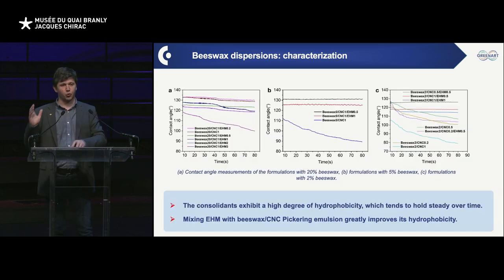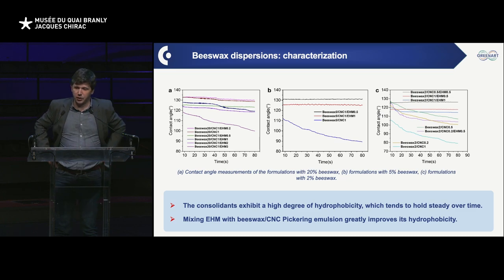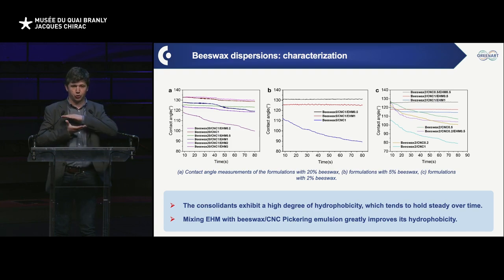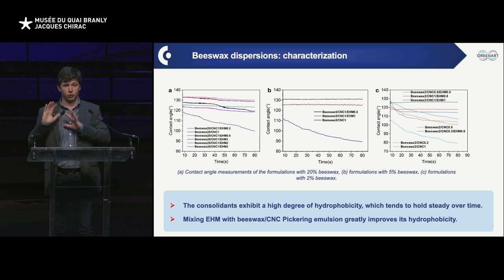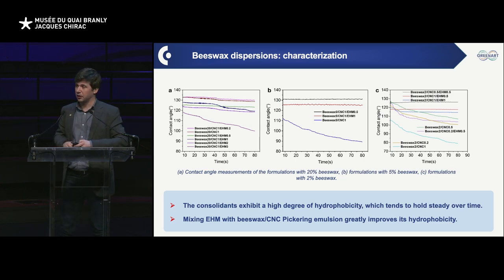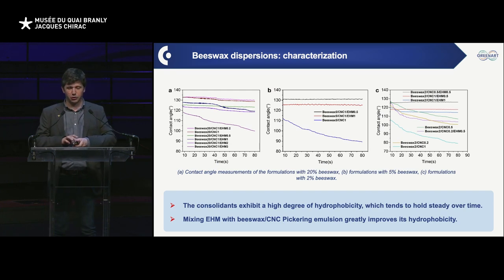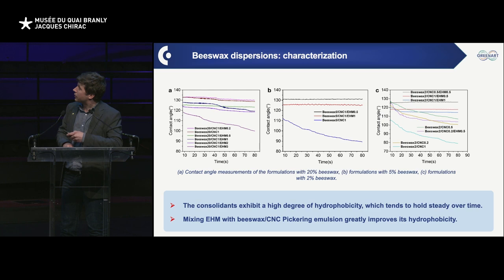Interestingly, I discussed the wetting properties and the properties of the film formed by our formulation, how they are behaving and performing. And one thing we discovered by doing that, so we did simply drop casting of the emulsion on the glass surface, we let it dry, and we measure the contact angle of water. That is as complicated as that. But then what we discovered is that we could achieve very high contact angle systems in that case. And interestingly, we started to spot a very neat feature. When we have the pure emulsion, like, if I'm not wrong, one of these over here, or even this one, this is the simplest example to discuss, beeswax 5 weight %, 1 weight % CNC, and then EHM in it or not.